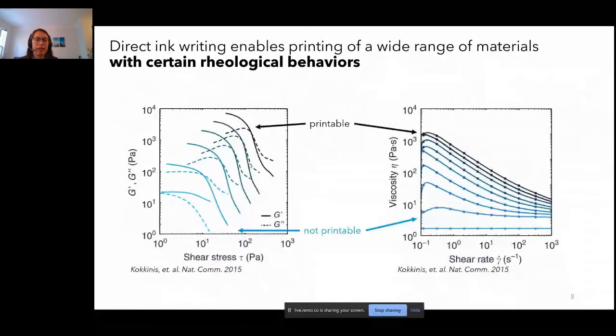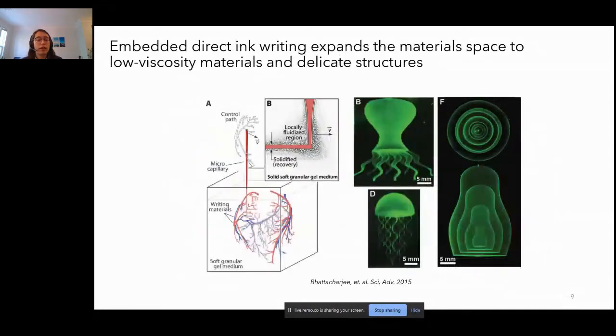Among these inks that are plotted here, at the top of the plot where we have these dark lines, those inks are going to be printable because they have a high enough yield stress that they will not just collapse under their own weight. However, at the low end of this plot, in these light blue inks, these are not viscous enough, they're not shear thinning enough, they don't have a high enough yield stress to be printable using direct ink writing. So that's where embedded 3D printing really becomes useful.